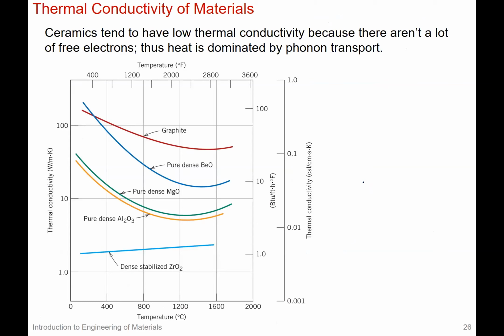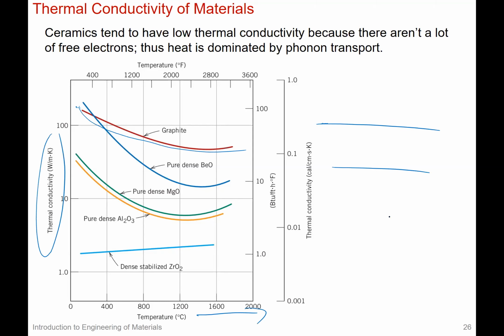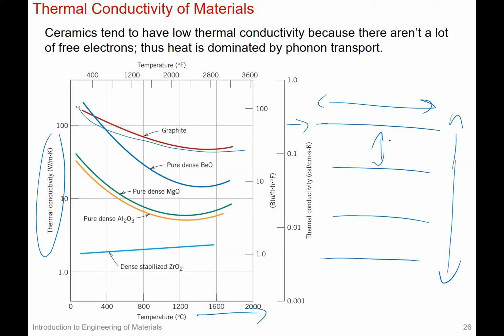So this slide should have been with the ceramic slide, but you could see here, there is a change in thermal conductivity as a function of temperature. And so, depending on where you are, you can see that graphite can actually have one value for, this must be in plane because it's higher than that of beryllium oxide, magnesium oxide, and alumina. Graphite is quite particular because, as you remember, there are layers of graphite. And so if you exfoliate one layer, that's graphene. So thermal conductivity is much higher in the lateral direction than, of course, in the transverse direction in between the layers of graphene and graphite. Right? Similar to polymers, because there's van der Waals type bonding in between each of the layers for graphite.